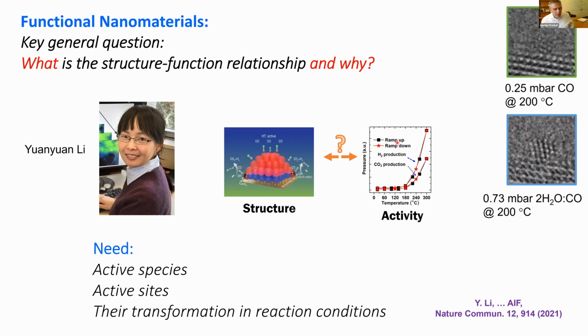The reason it's really an interesting question, especially in nanomaterials, is because there's not one, not two, but maybe several things that may change at the same time while you activate the catalyst and when it undergoes or participates in reaction. For example, at the top you see a collection of frames from in situ electron microscopy experiments, where carbon monoxide was flown at a platinum nanoparticle on ceria. And you see that the image is so blurry, you can't make out any positions of any atoms there. But once you add water to make it a water gas shift reaction, you start seeing the fringes, you start seeing atomic positions. And the only change was that you added water to the reaction mixture.